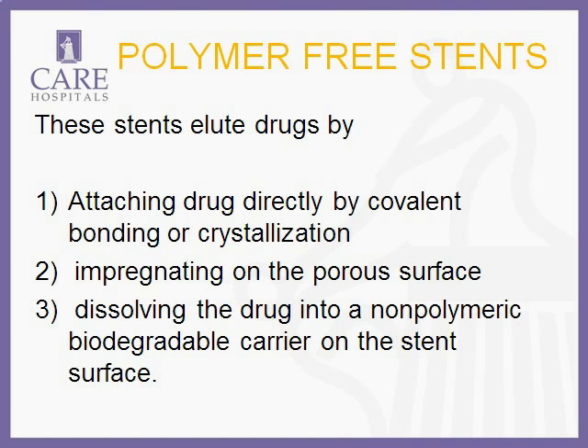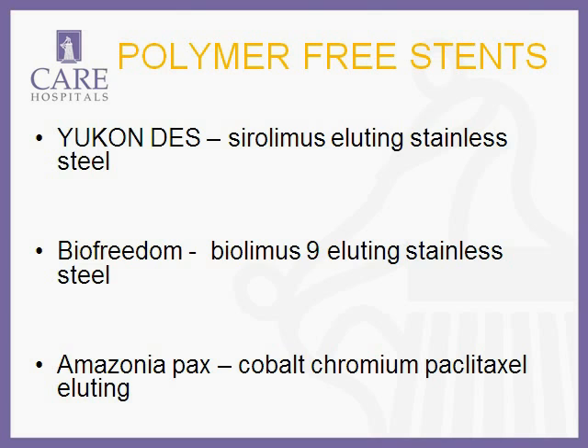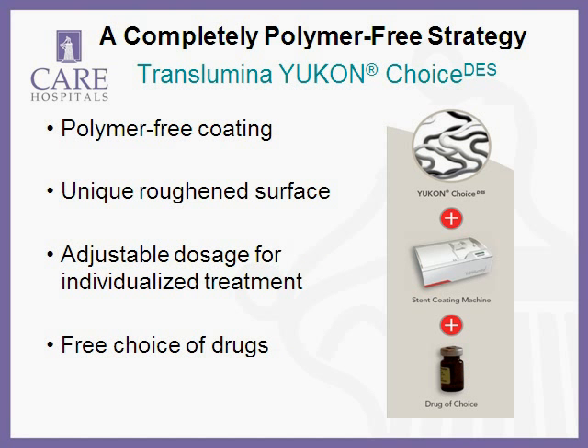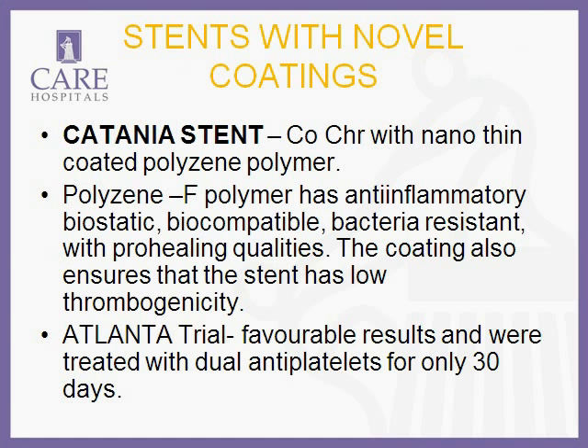Now, these stents elute by attaching the drug directly by covalent bonding or crystallization, impregnating the porous surface, or dissolving the drug into a non-polymeric biodegradable carrier on the stent surface. It is a cobalt chromium one, whereas both of the rest are stainless steel ones. Here, as we see, it's a polymer-free coating. It has a unique roughened surface on which the drug is actually coated, and we have a choice of which drug we actually want to coat as well.